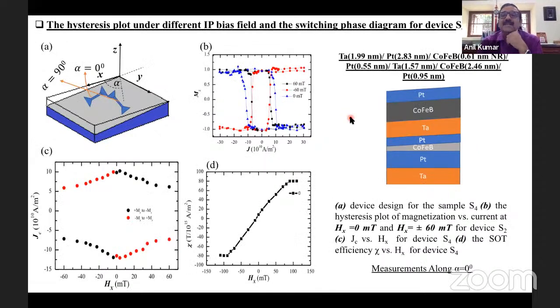Now I go to another structure. For example, now I'm going to put a cobalt and boron layer. In the previous one, you saw that when I applied the current along the thickness gradient direction, I had to apply an in-plane magnetic field. Now, my question is, can we apply an in-plane magnetic field just by putting a ferromagnetic material near to that? If I have a ferromagnetic material which is in-plane magnetized, you know that there will be stray magnetic fields, and that stray magnetic field a couple of nanometers away can give an equivalent in-plane magnetic field. And indeed, that is what you are seeing here.